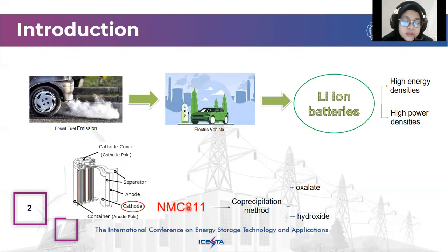Some compositions of the NMC cathode are 622 and 811. This study used NMC 811 because it has a larger capacity than 622. NMC 811 was synthesized using the co-precipitation method because this process uses low temperature and makes it easy to control particles, so that the time used is shorter. In this study, the characterization of NMC 811 will be compared between the co-precipitation method using oxalate versus hydroxide.